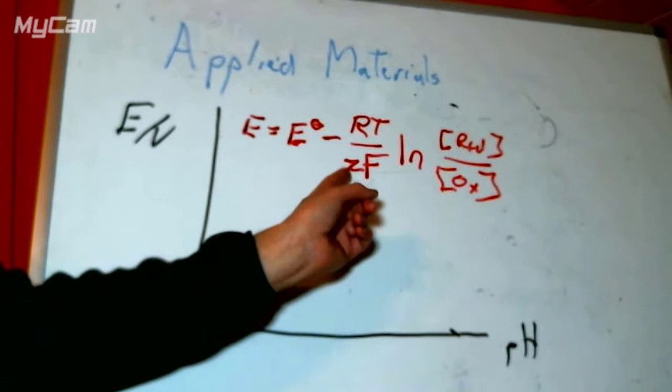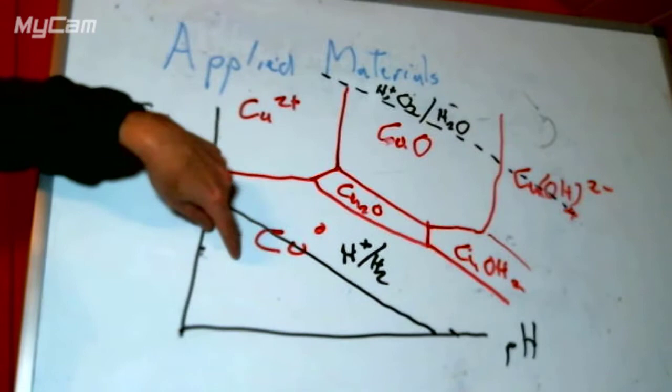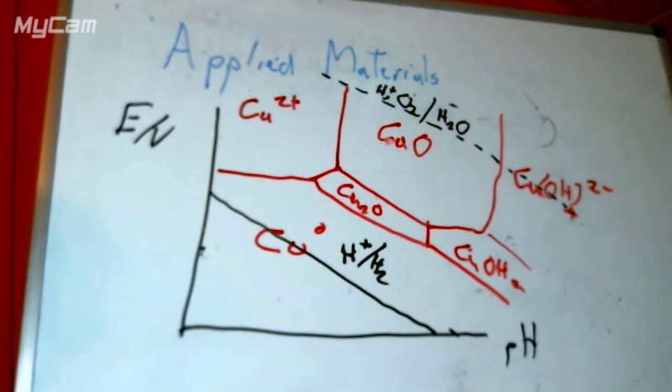We can get the water lines and their diagonals with a certain gradient — the gradient is usually the z value, the number of electrons. Here is an alternative diagram for a different metal — copper. We can see the line for water here. Copper is unable to reduce water; it sits above the water line. So if we put copper zero into water, it can't destroy the water. It is, however, susceptible to oxidation by oxygen in the water.